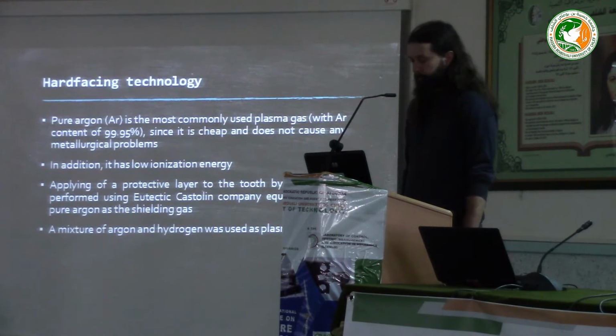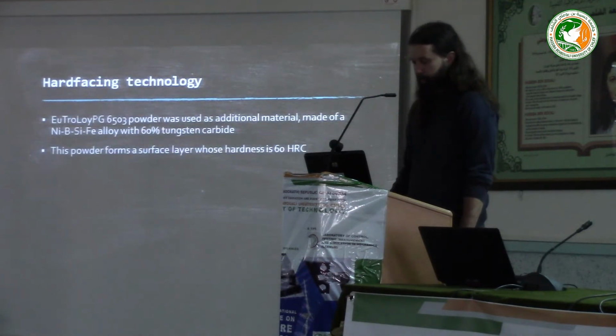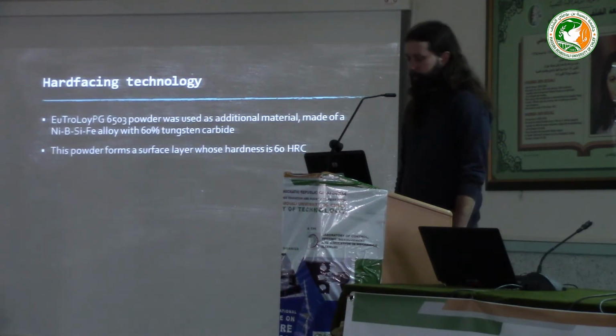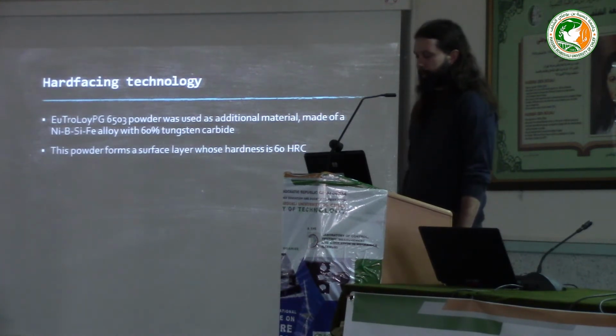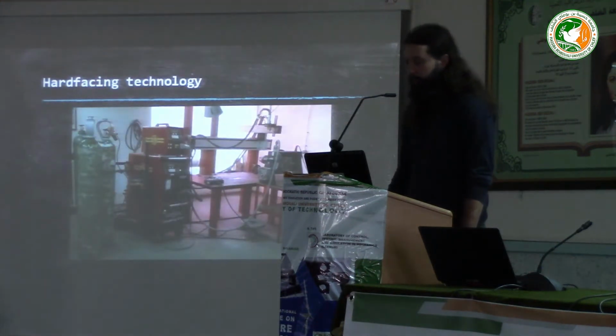Applying of a protective layer to the tooth by plasma, in this case, was performed using Eutectic Castolin equipment, and pure argon was used as the shielding gas, whereas the plasma gas consisted of a mixture of argon and hydrogen. Here, you can see the alloy which was used as an additional material and is made of a nickel, boron, silicon, iron alloy with a very high tungsten carbide content of 60%. Because of this, the surface layer formed by the powder can achieve hardness of up to 60 HRC. And here you can also see what the equipment that was used looked like.